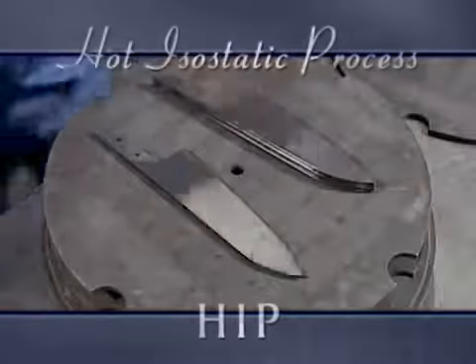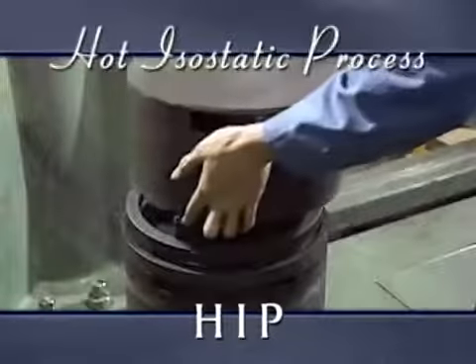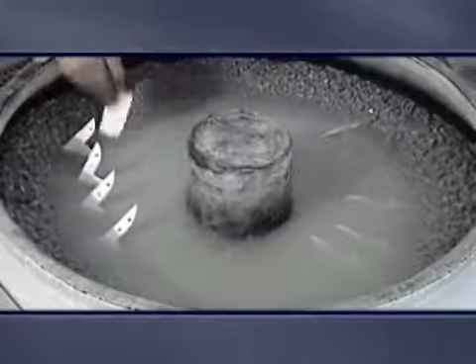At temperatures in excess of 1,000 degrees, the furnace hardens the material. Exact control of the exposure time at each temperature is critical to achieve the desired hardness. To create the Kyocera hot isostatic process HIP blades, one additional manufacturing process is performed. The blades are polished in tumbling vats filled with green carbide rocks. The blades are then ground to smooth out all edges.